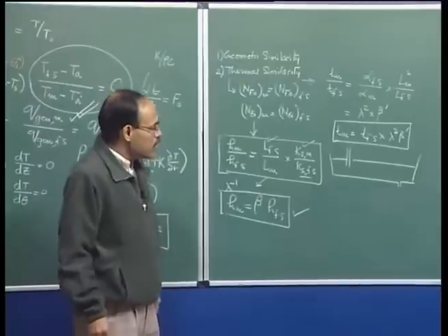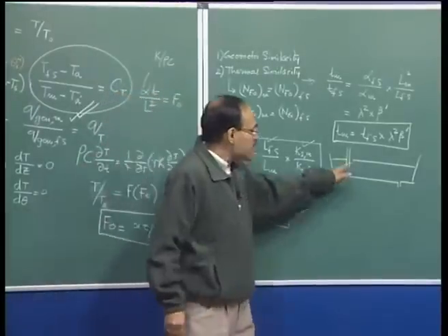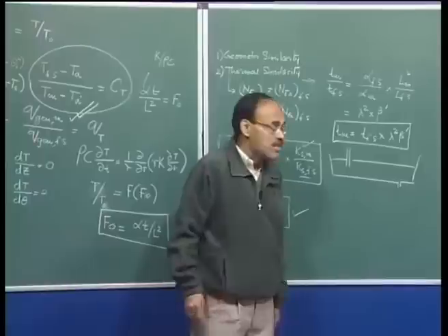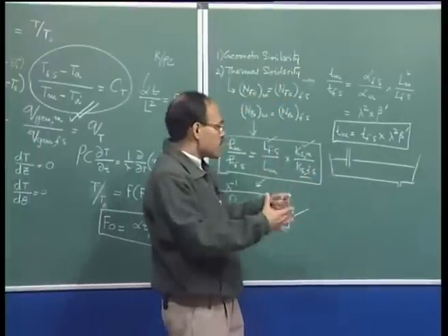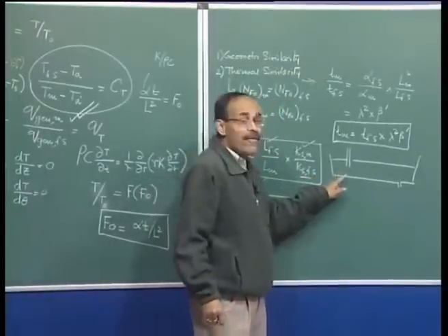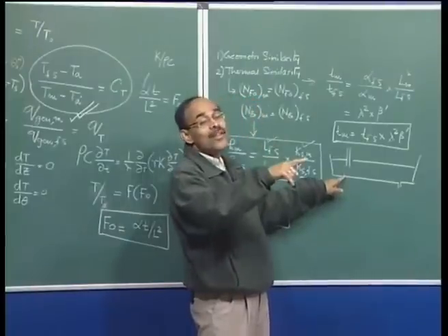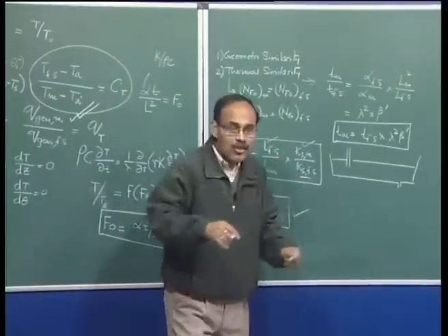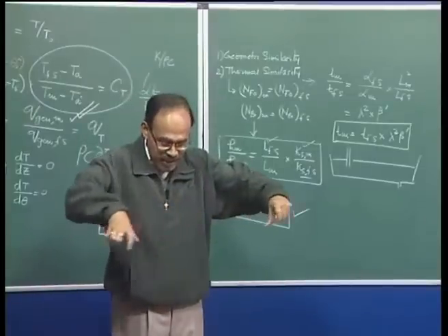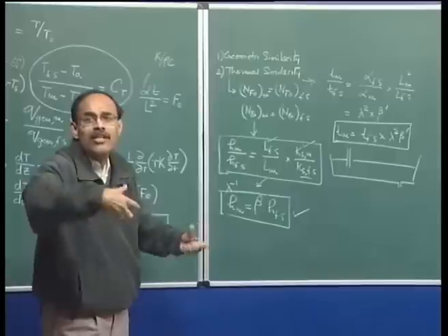Now, in this case, although I can scale down on the basis of the governing equations, get the numbers and maintain the equivalence, it will be very difficult for me to maintain the equality which will come out on the basis of the boundary conditions, because you can imagine that if you have a 1600 degree molten metal in a vessel, a tundish, you have some finite amount of heat loss.